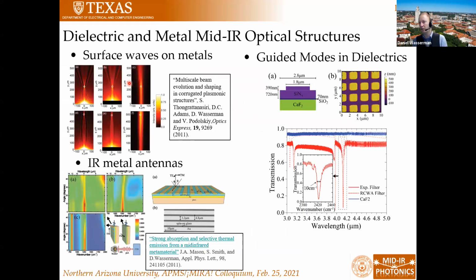So of course we can use traditional metals. Metals have somewhat unique properties. They can be highly reflective. In the shorter wavelength range, they can behave as plasmonic materials, but we can use metals, for instance, to support surface waves. This is work that I did with my colleague Victor Podolsky, where we showed that we could essentially use a corrugated surface to effectively focus or steer scattered light from surface waves. We can design essentially IR antennas, which in this case we use to engineer selective absorption and then selective thermal emission. So we could engineer surfaces that would emit at certain wavelengths in the infrared.